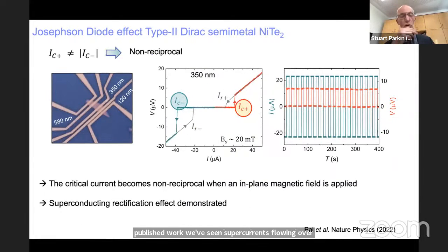But you see these are enormous separations between these niobium electrodes, and on the right-hand side, you can now see the voltage between those two niobium electrodes as a function of current, and you can measure the critical current for superconductivity. And in this case, in the absence of any external magnetic field, the critical current for current flowing to the left and to the right are the same. But you can see the critical current decreases with increasing separation. And now, subsequent to this published work, we've seen supercurrents flowing over more than a micron spacing between these electrodes. These are enormous distances. So why is this interesting?